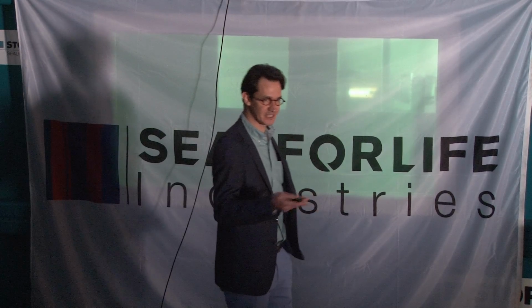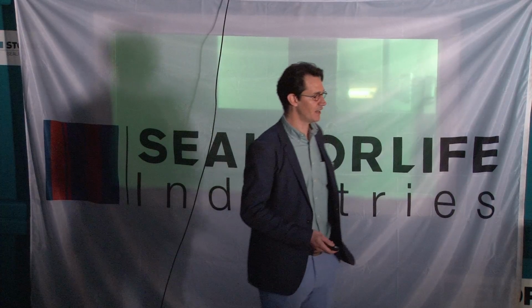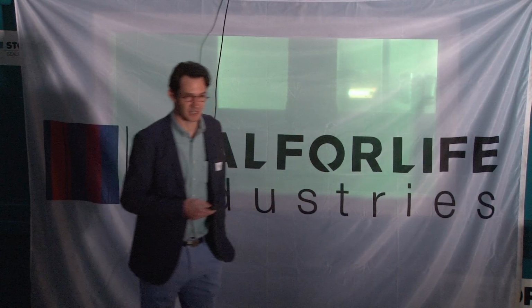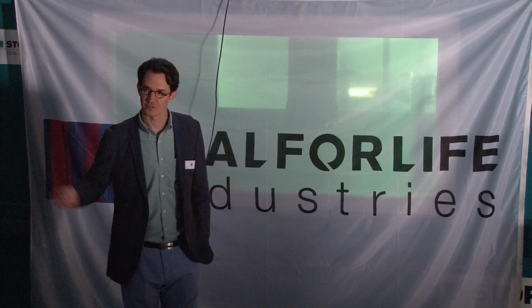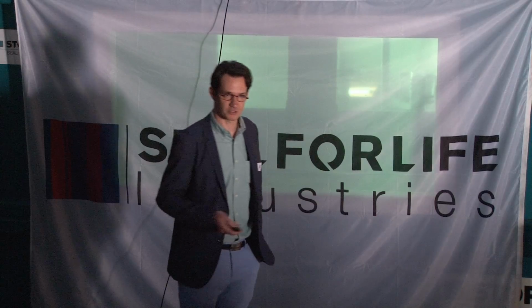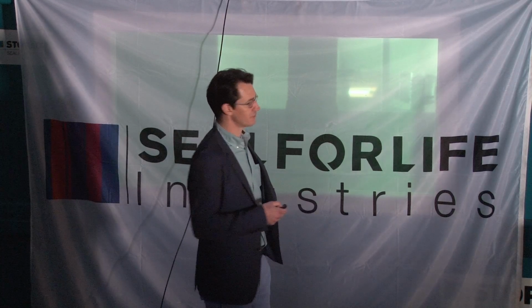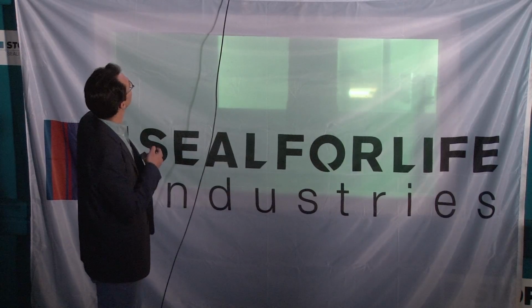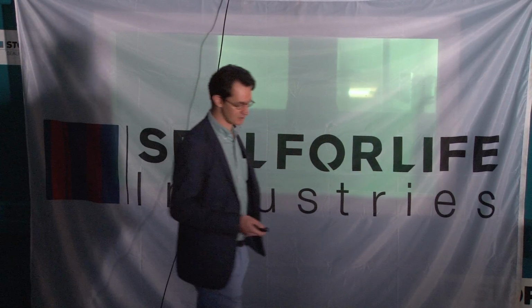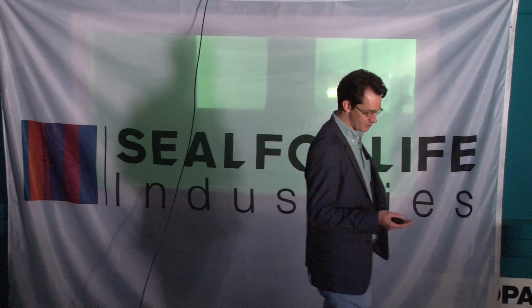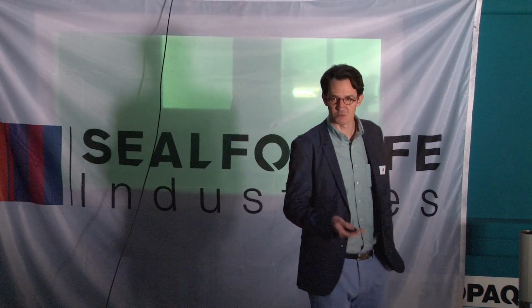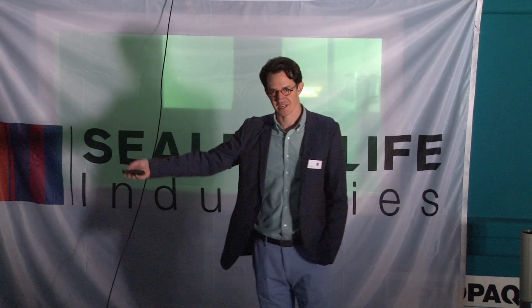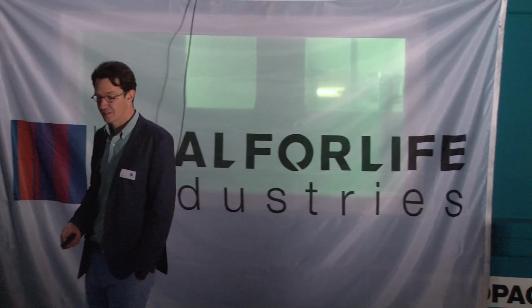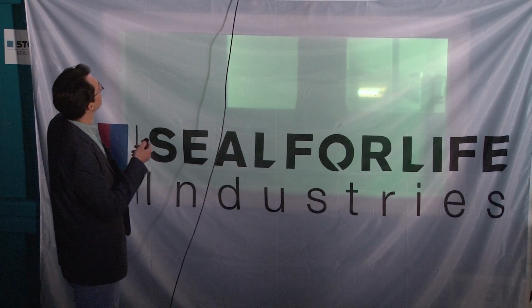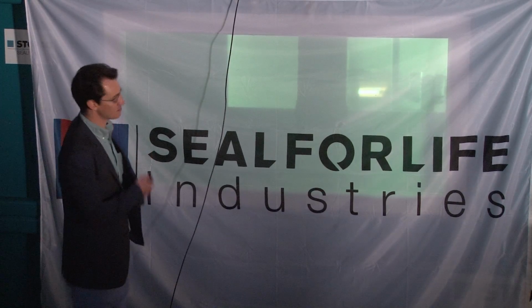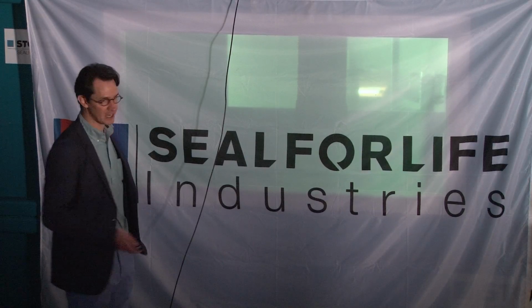And unless the coating self-heals, self-repairs itself, then you have expansion of corrosion. It just continues until all the coating is gone. So by having something which self-heals, here's an example. And you remove this mechanical protection on top of it. Underneath there is a coating which flows, doesn't age, so it will flow over time, and therefore it will self-heal. So if I took the example of a tree, imagine that the pipe is a trunk, this is the bark of the tree.